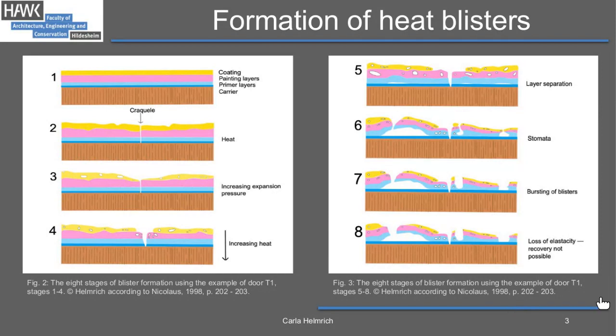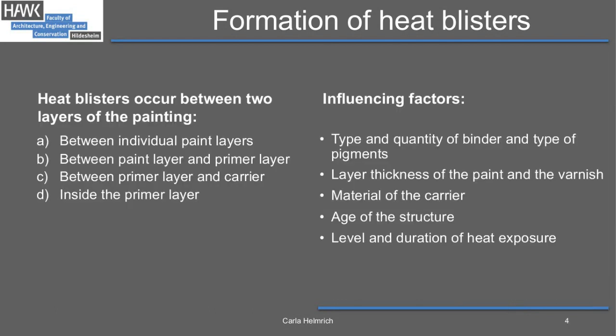In summary, it can be stated that the heat blisters occur between two layers of the paint, either between individual paint layers, between paint and primer, between primer and carrier, or even inside the primer layers. Influencing factors can be the type and quantity of binder and the type of pigments that was used, the layer thickness of the painting and the varnish, as well as the material of the carrier. Other factors for the formation of heat blisters can be the age of the structure and the level, or even the duration of heat exposure. All of these factors determine the layers in which the blisters occur, their size, or also their appearance.